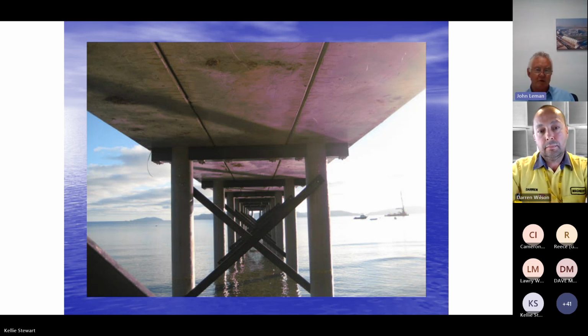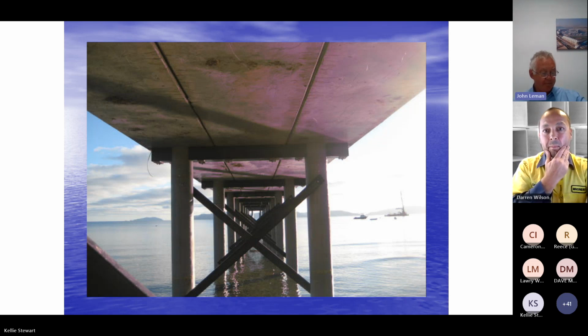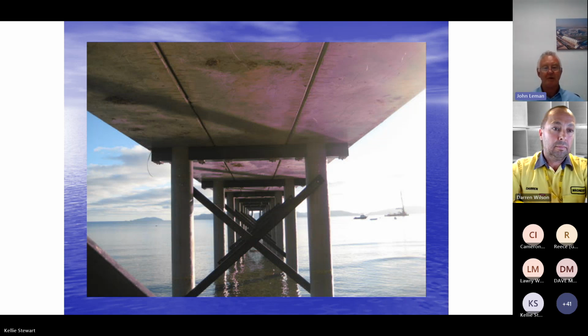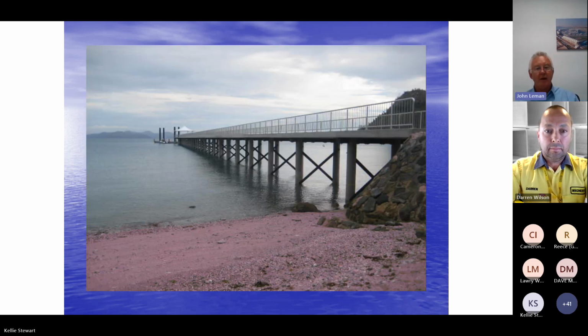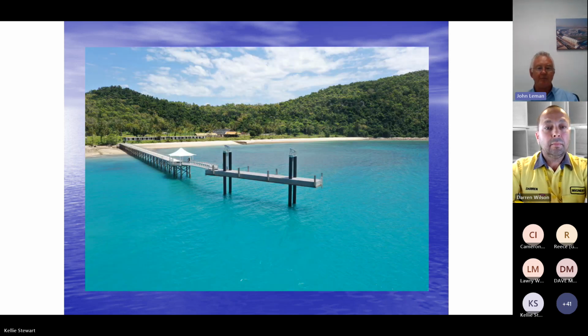On my first inspection, I noticed a bit of rust just under where the stainless steel bolts were, but actually they used a diamond core bit on a steel mandrel, and it left some steel on the hull. I'm a bit disappointed that we saw a bit of rust there, but it wasn't anything to do with the materials being used. So that's the completed jetty there. And then you've just got a floating pontoon at the far end of it. But you've got a fixed jetty there that's no maintenance, no carbon steel, so it's going to be there for a very long time.